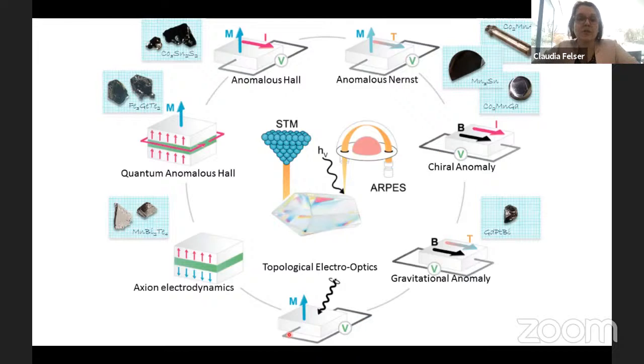So I want to guide you through this complex measurement. But the first thing, and you maybe understand from what you learned already, is that if we have grown our crystal, we investigate angle-resolved photoemission, because this is a method with which we can check whether the calculated electronic structure, which we did with density functional theory or even beyond, for these magnetic and correlated systems, is really the experimental electronic structure. It doesn't make sense to measure something if we have not proven that our calculations are correct.